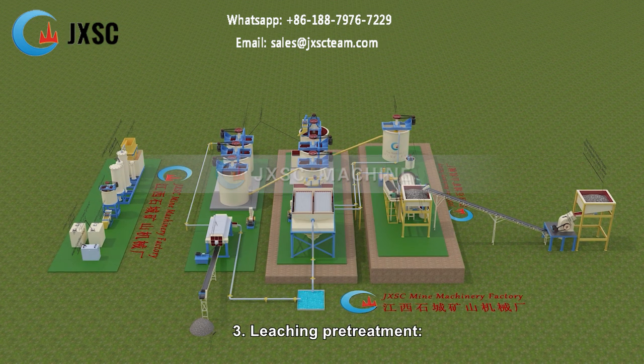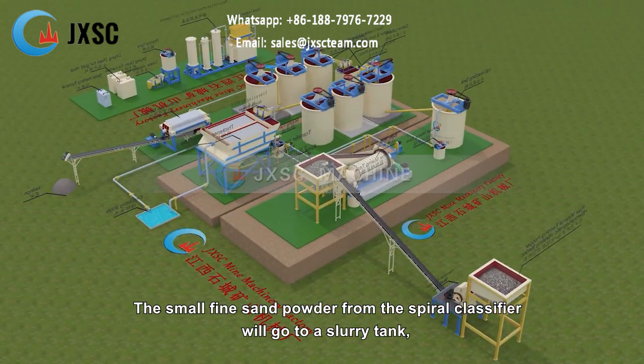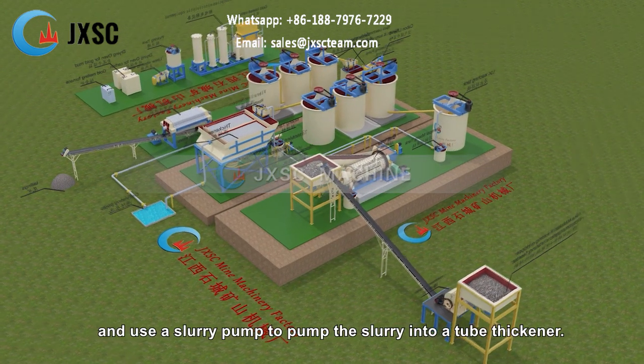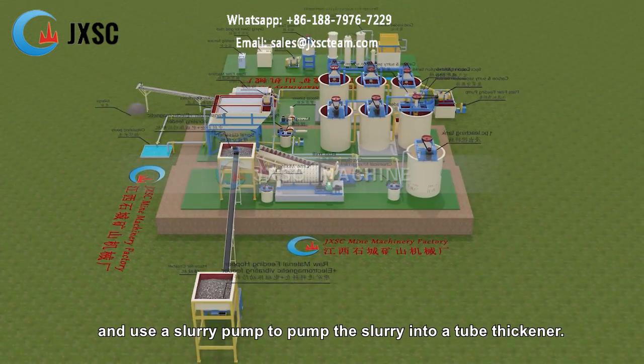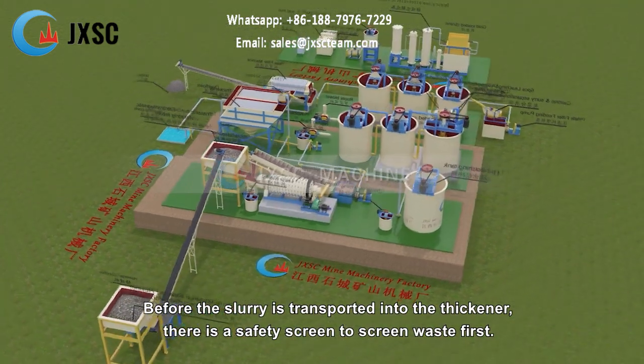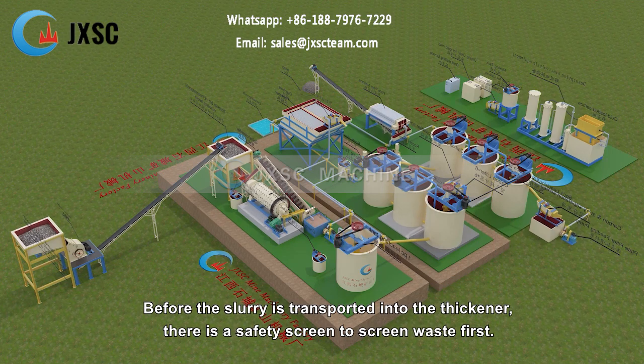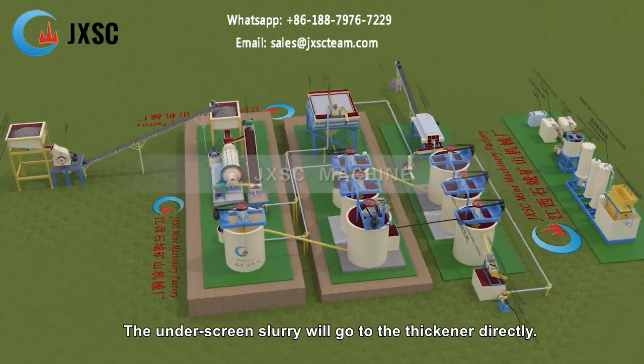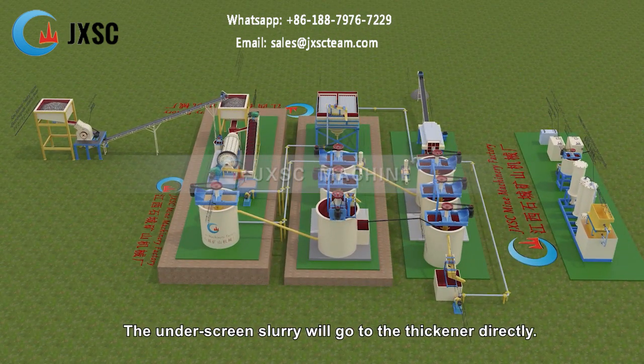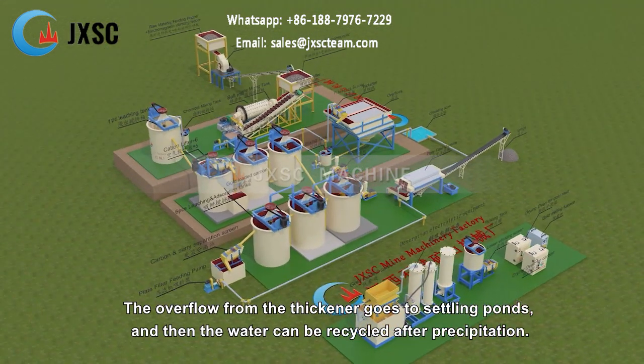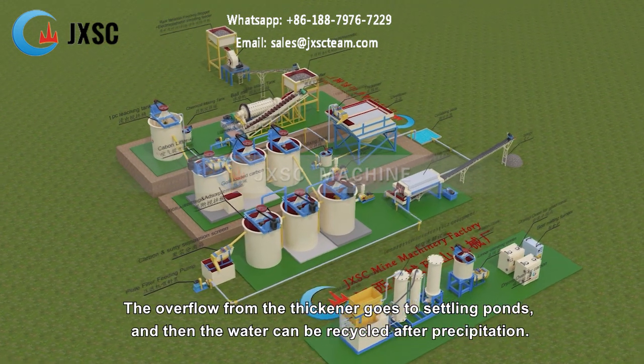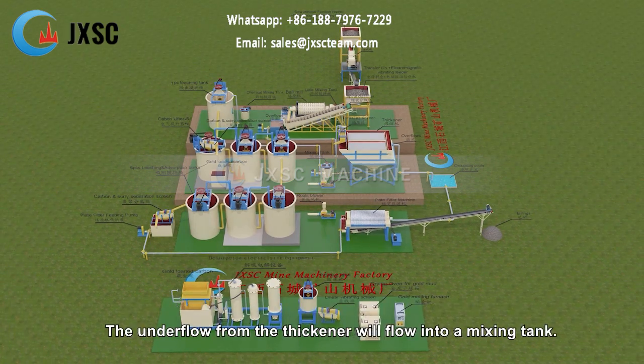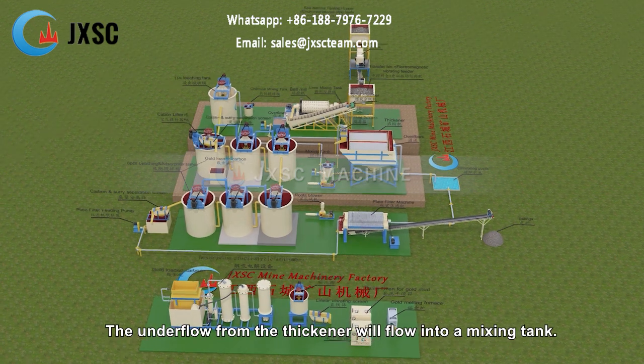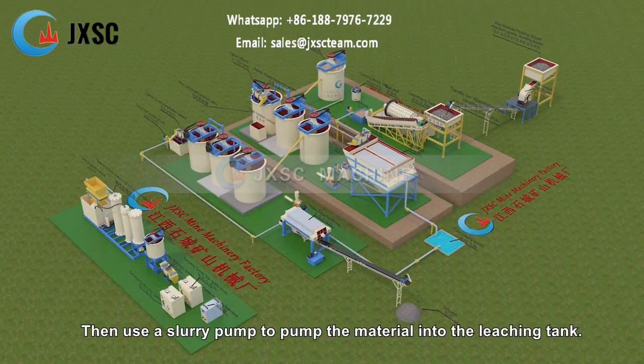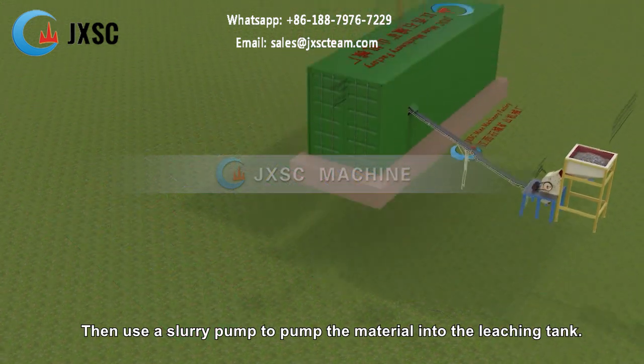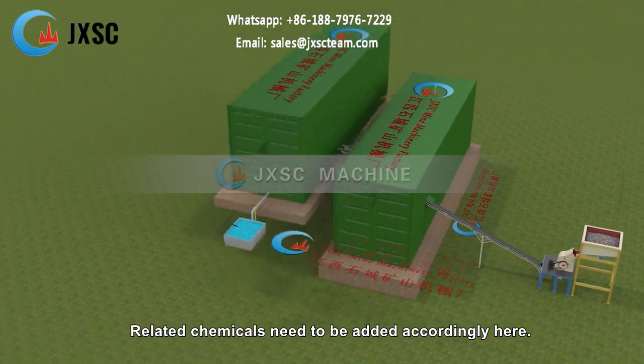3. Leaching pre-treatment. The small fine sand powder from the spiral classifier will go to a slurry tank and use a slurry pump to pump the slurry into a tube thickener. Before the slurry is transported into the thickener, there is a safety screen to screen waste first. The underscreen slurry will go to the thickener directly. The overflow from the thickener goes to settling ponds, and then the water can be recycled after precipitation. The underflow from the thickener will flow into a mixing tank. Then use a slurry pump to pump the material into the leaching tank. Related chemicals need to be added accordingly here.